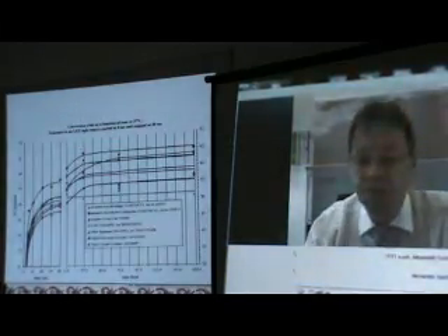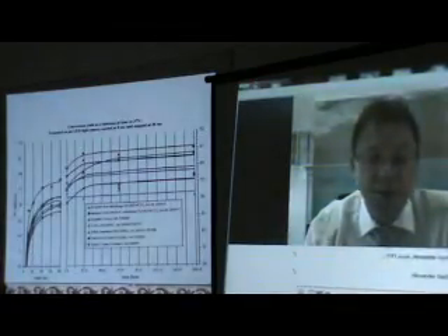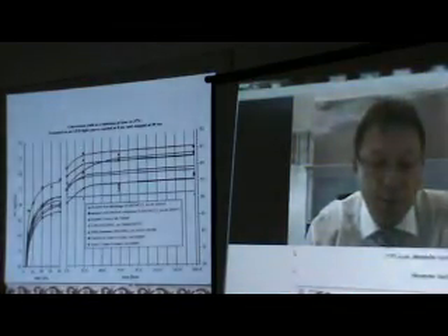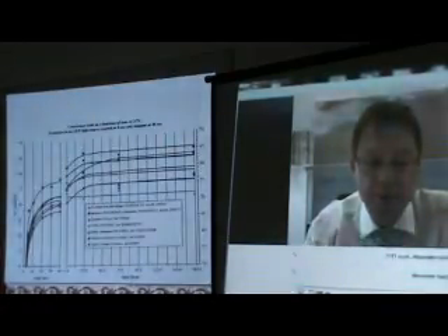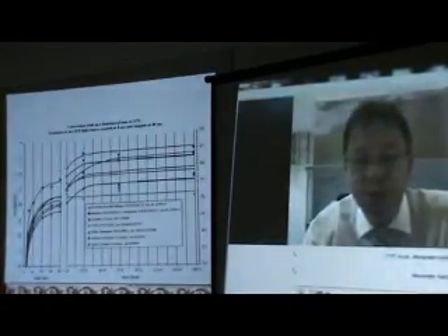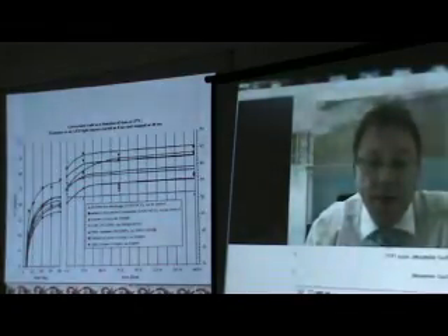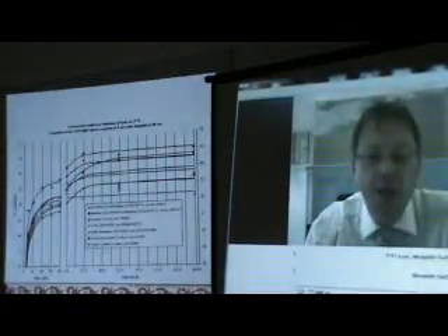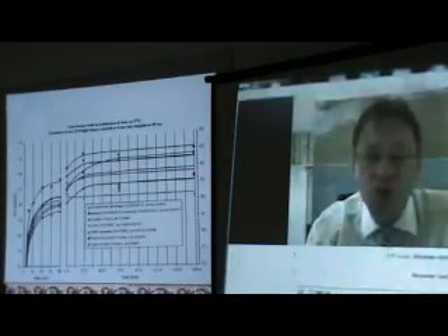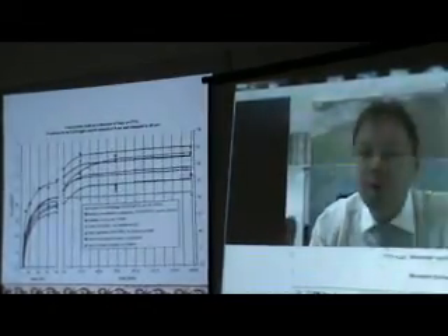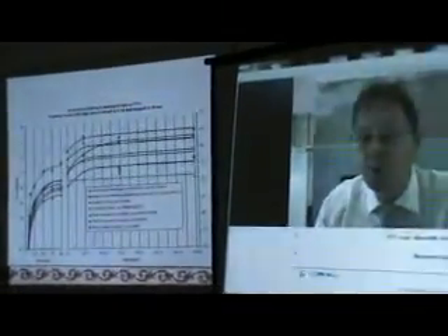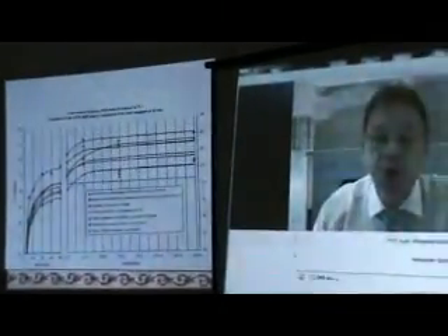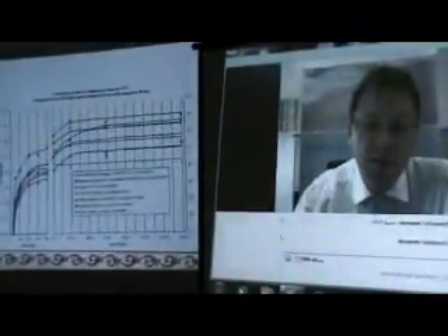Actually, as soon as you use the polymerization lamp on your composite, you will actually start the chemical process. From then the monomers will convert to polymers. But I must tell you that in general, this conversion can never be 100%. Even if you polymerize for 1 hour, it does not change anything. There is a certain chemical barrier which makes that you cannot go over a certain percentage of conversion rate.